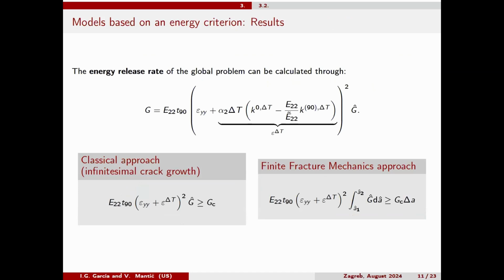With that, we can calculate the value of G with actually the same strategy as before. So G is given by some parameters, but with respect to the load, it's given by the addition of the mechanical strain that we are applying and this term, which again is the same as before, the equivalent strain, let's say, that comes from the residual thermal stresses. With that, we can apply directly any kind of energetic approach that is based on G in some manner. But that is the case of the previous theories.